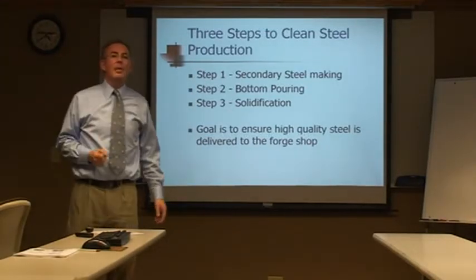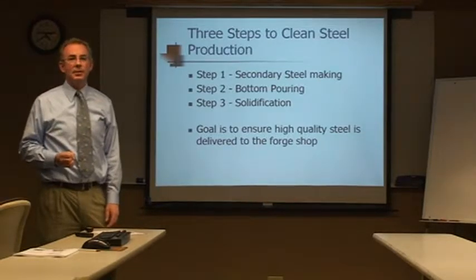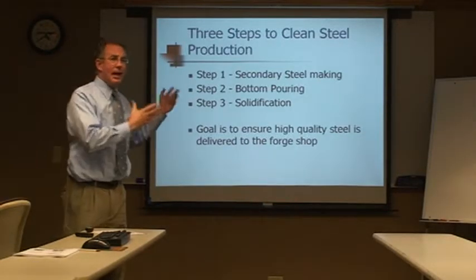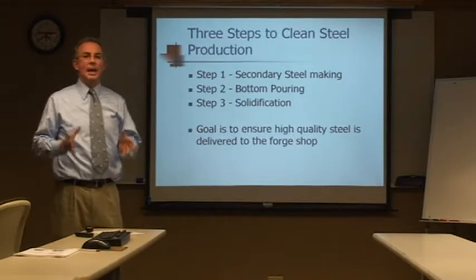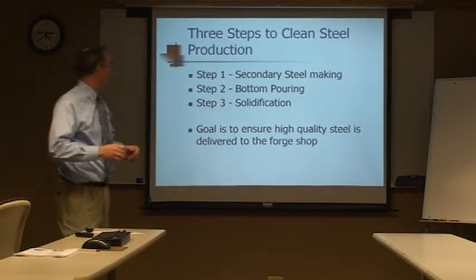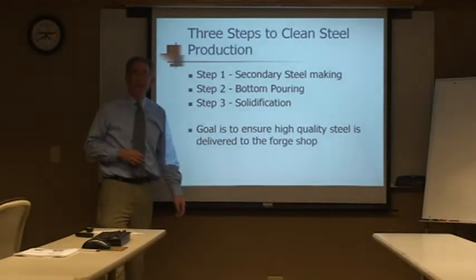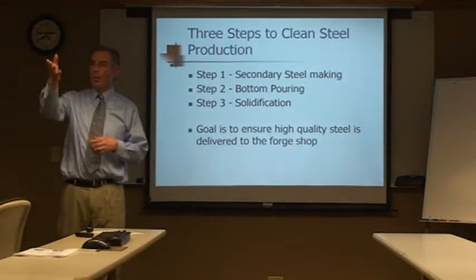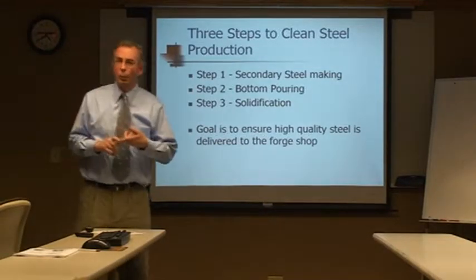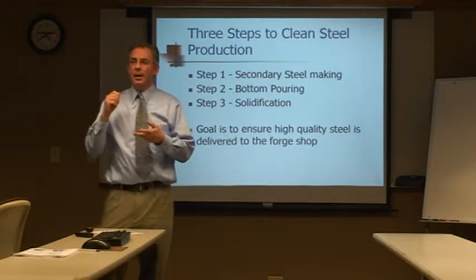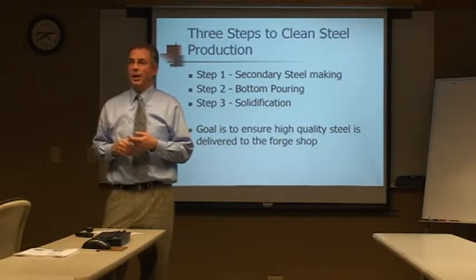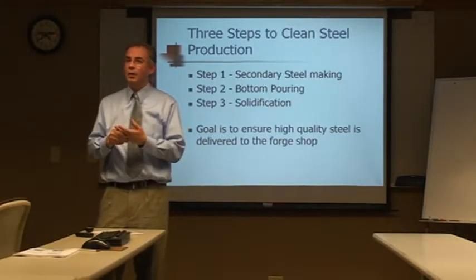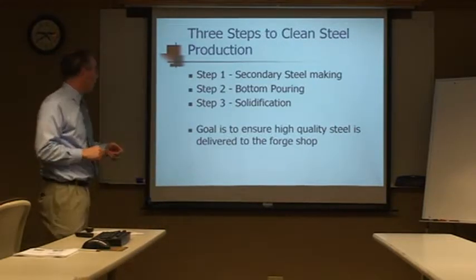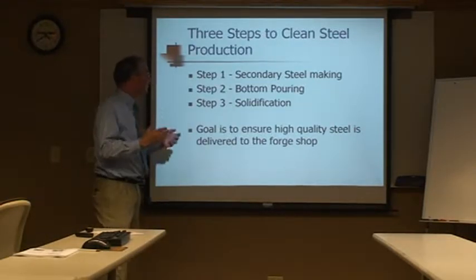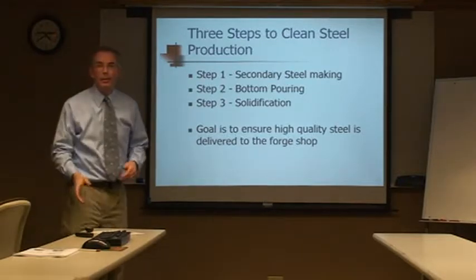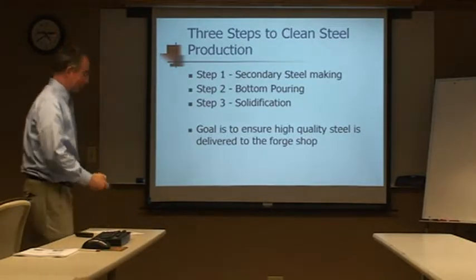Step 2, we can undo that in a heartbeat with a bottom pour practice. So all that hard work, all that time and effort, it goes by the wayside if we don't take care when we pour the ingots. And then finally, step 3, clean steel during solidification, making sure when we have our molds that we have proper mold design, that we have proper practices, solidification times, not disturbing the mold, making sure we don't, again, undo what we've already done. And our goal is to ensure high quality steel is delivered to the forge shop consistently.